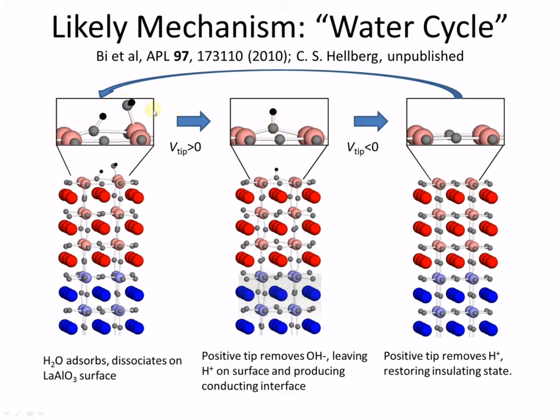So we believe that water plays a critical role in the writing process, and the water will naturally adsorb onto the lanthanum aluminate surface. But if a water molecule is adsorbed like this, it's still electrically neutral, so it's not actually charging the interface and is not expected to create electronic states at the interface. So it's not charging the top surface. However, we can remove this hydroxyl group here with the application of a positive voltage, leaving the hydrogen terminated surface here, and this H plus here is going to attract an electron to the interface. And then by changing the polarity of the voltage applied to the tip, we can then remove that hydrogen and then leave a clean bare surface where another water molecule is free to come down and grab onto the surface. So that would take us back and allow this cycle to continue.